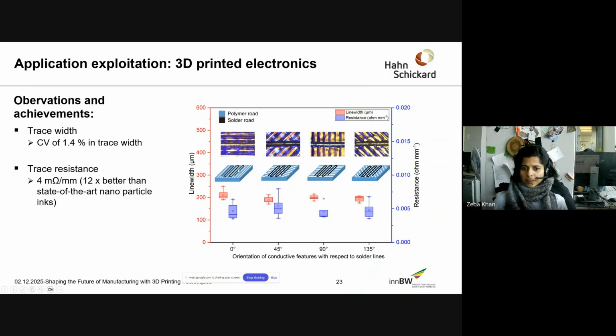We did different orientations because FFF, as you know, is not a very fine resolution printing technology. Rather, it presents a crude or rough surface area. And therefore, this is also very important, to make sure we are able to test our capacity in different orientations of the FFF printing. So these on the top that you see are images of printed traces, which were formed by